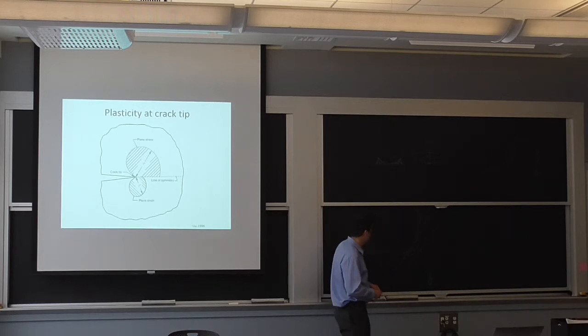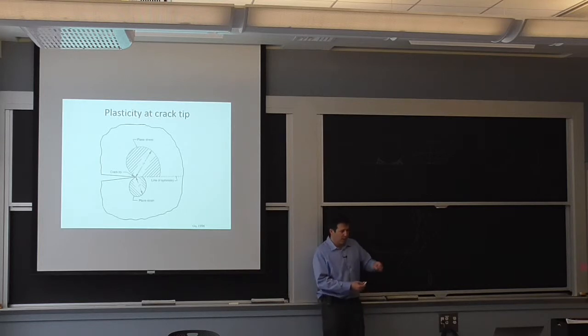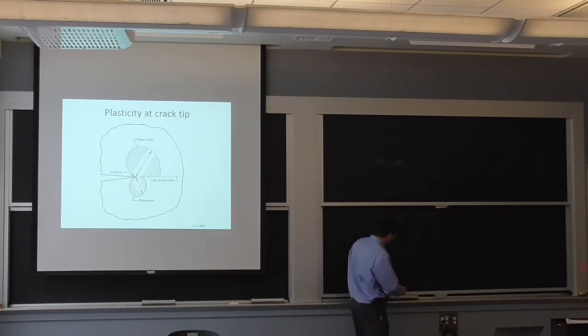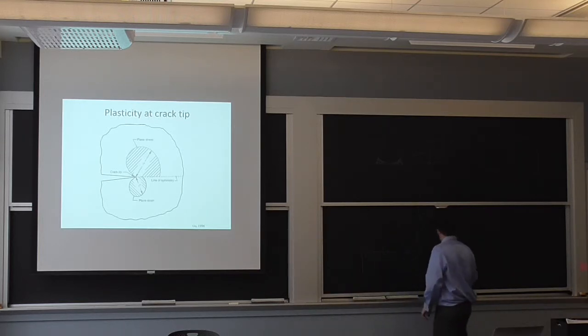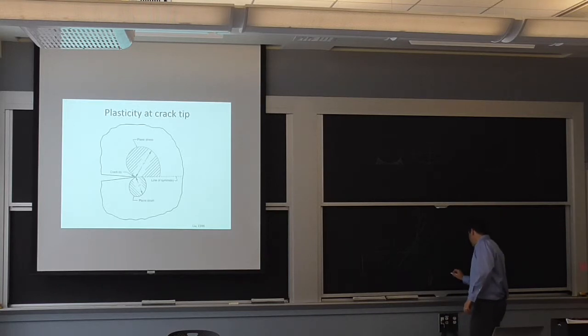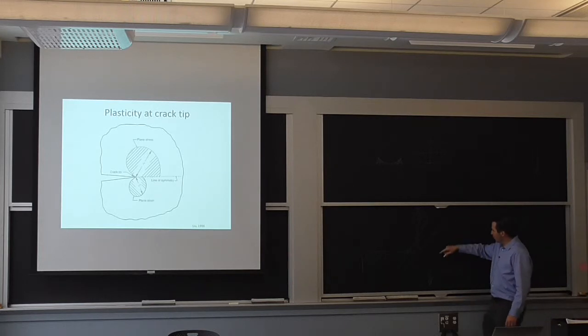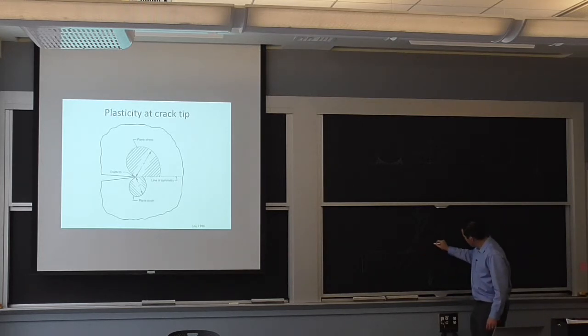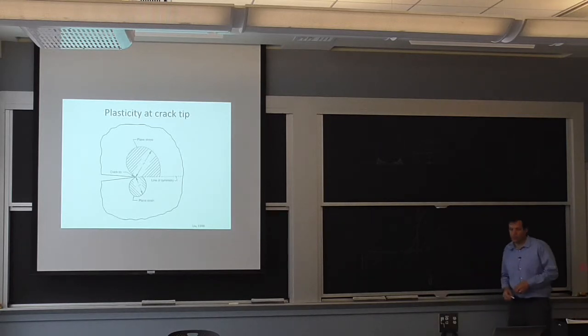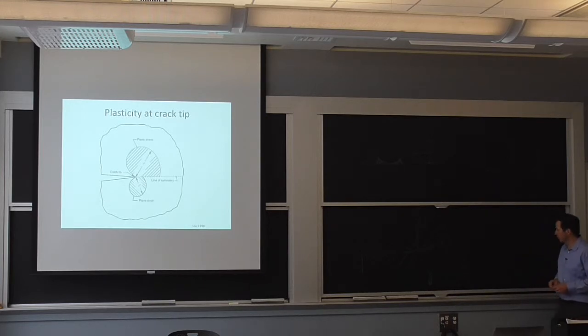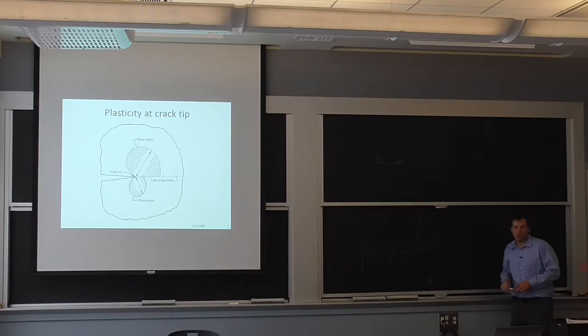Let's say they machined it pretty tight and by applying even something like 20% of the yield strength, if you sharpen up here you can be at plasticity at that sharp point if you have a little torsion or depending on what the condition is. So the nominal load and the local load can become very, very different.